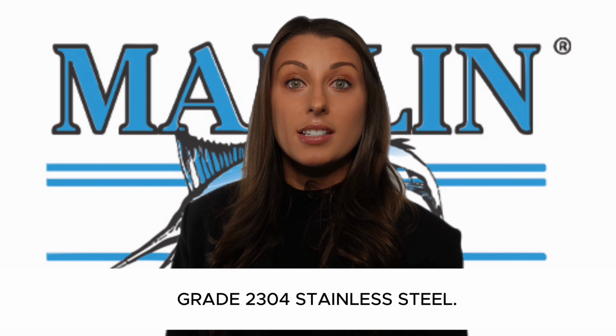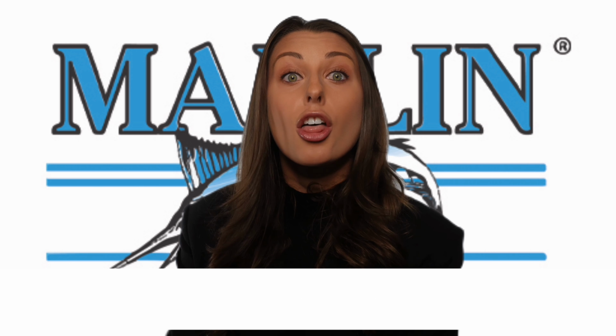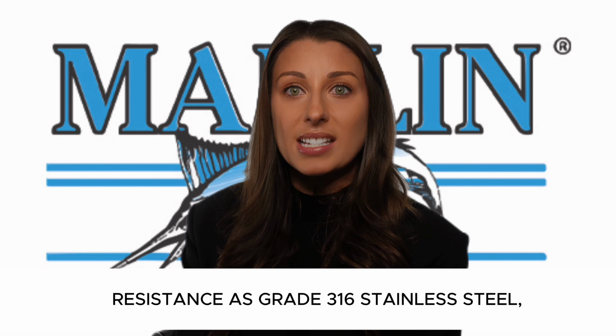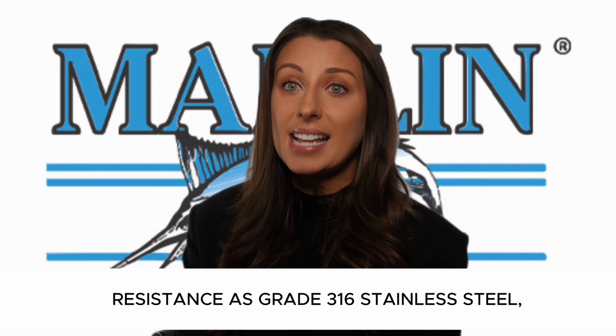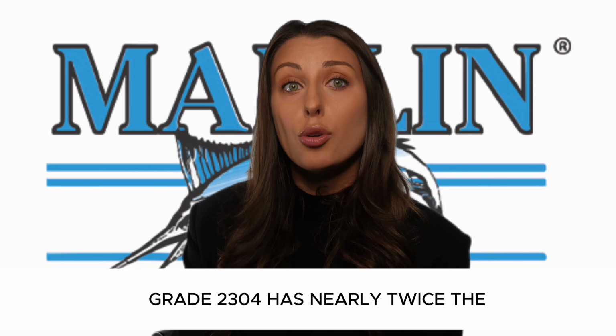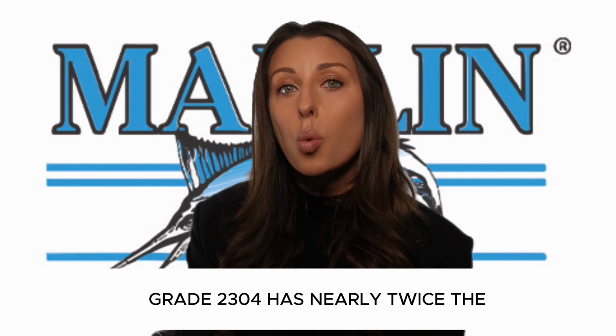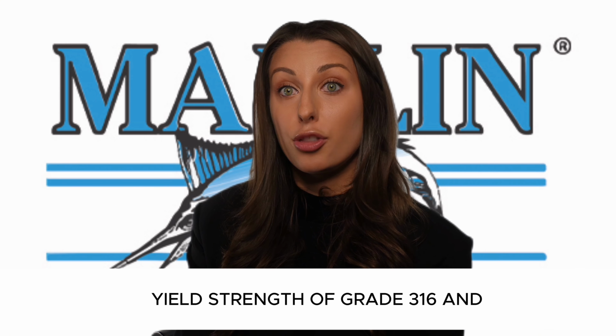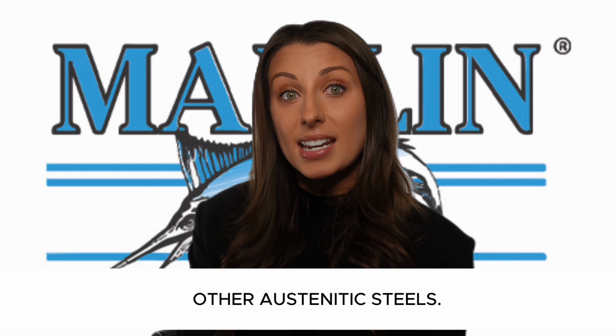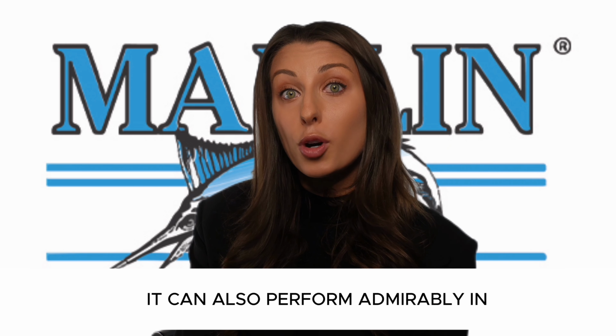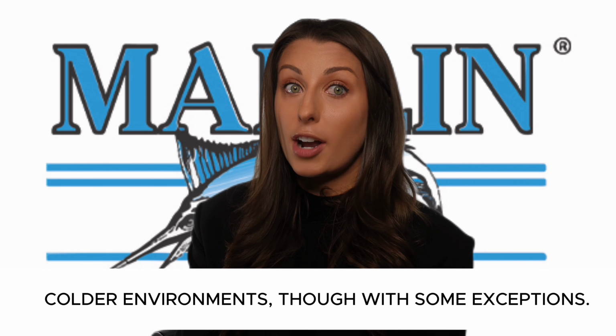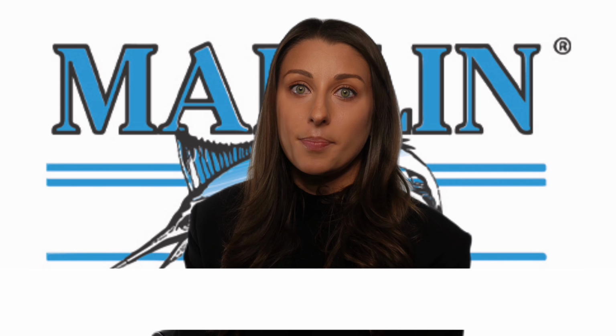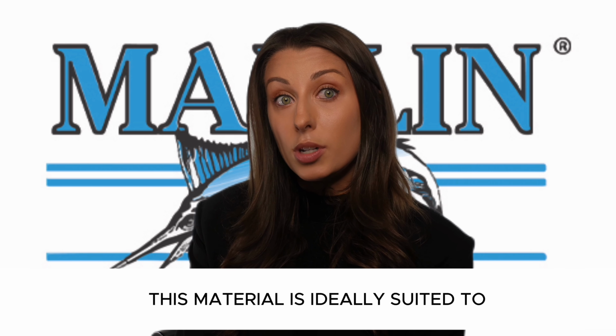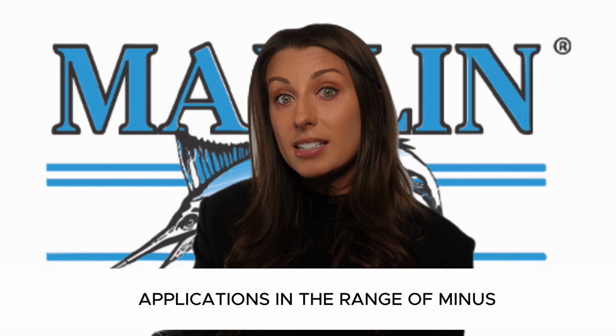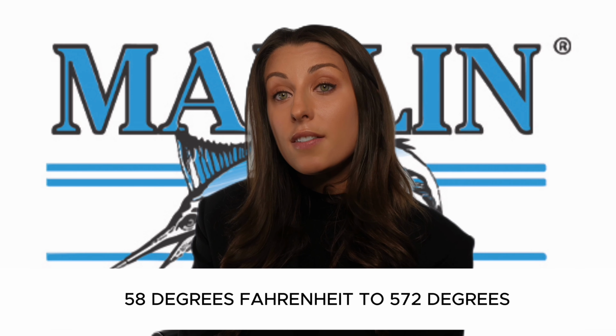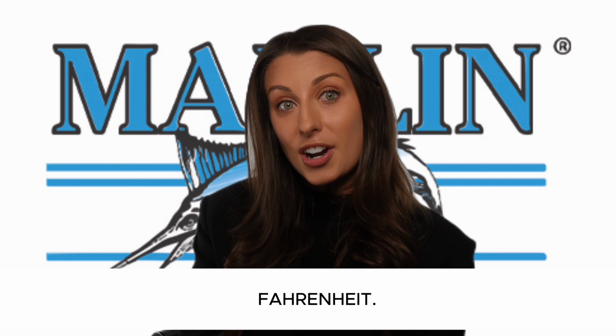Grade 2304 stainless steel. Though it has the same corrosion resistance as grade 316 stainless steel, grade 2304 has nearly twice the yield strength of grade 316 and other austenitic steels. It can also perform admirably in colder environments, though with some exceptions. This material is ideally suited to applications in the range of -58 degrees Fahrenheit to 572 degrees Fahrenheit.